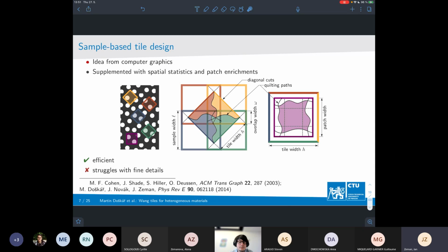What we also added to this computer graphics consideration is that we tried to tune the optimal overlap width in order to make sure that the spatial statistics of the original and reconstructed system match as closely as possible, like in the previous approach. And what we also experimented with is that, on top of that, we selected independent pieces of the structure we are working with and patched them into the tile interiors to add even more diversity to the set. If you use that, it is a highly efficient procedure because it was invented in computer graphics. It is representative because you work directly with microstructural samples, so you do not construct them artificially, you have them.